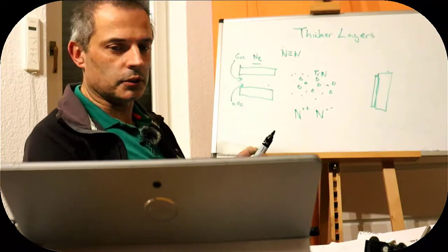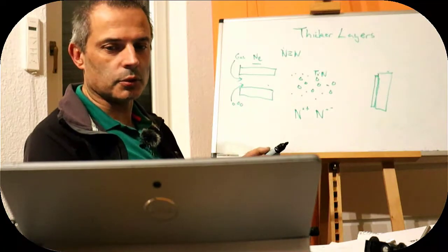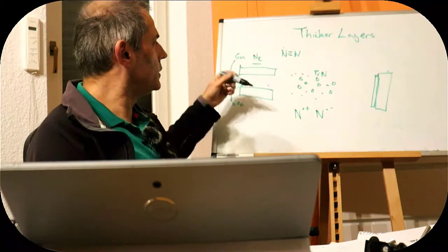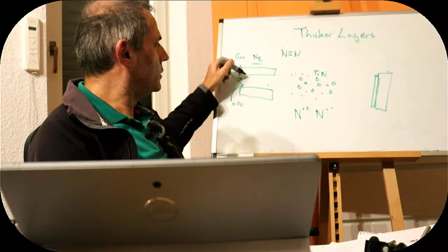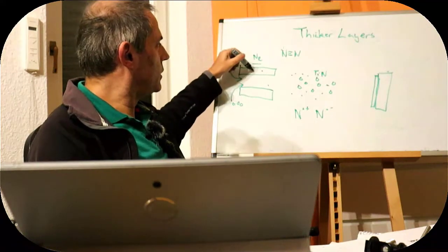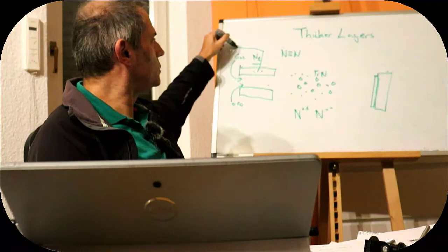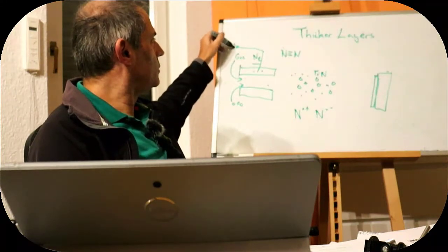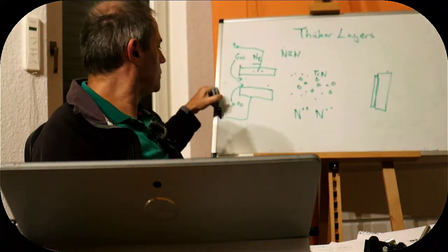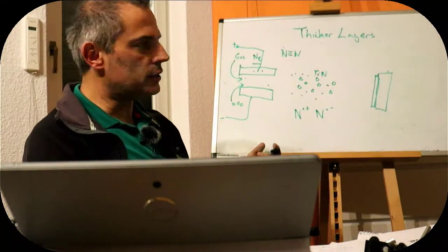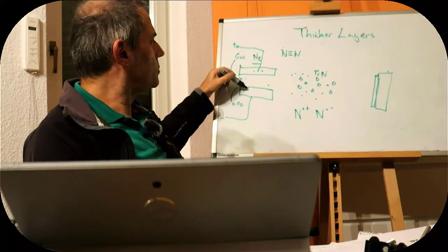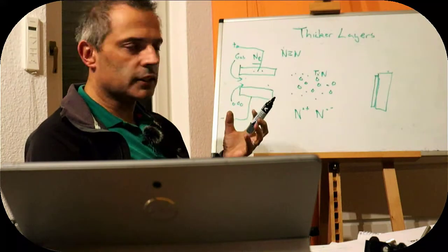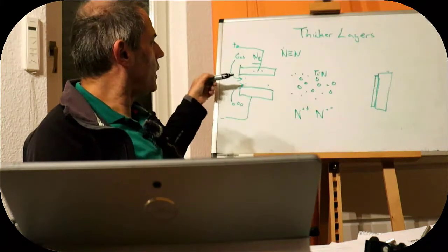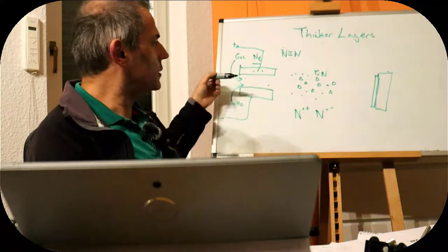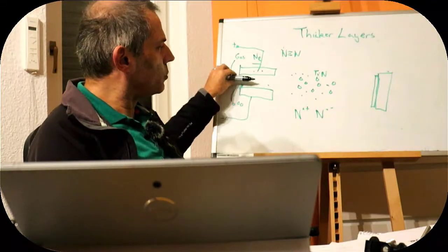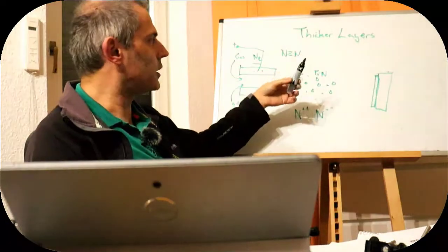If we don't use a fire, we can use a plasma instead, so we can use an electric fire, and then we can generate a plasma. We're going to make it short, so we've got our, let's just make it plus and minus. It obviously wouldn't be a DC plasma. We light a little plasma in the end. That causes the gas to expand explosively, and we would have to close the end in some way to stop it blowing out the back, and that will push our titanium nitride out of the front.